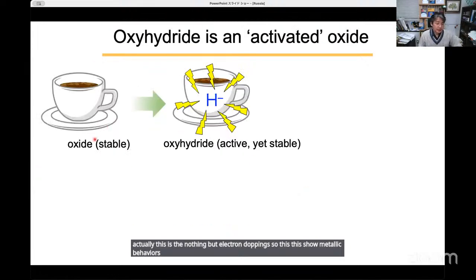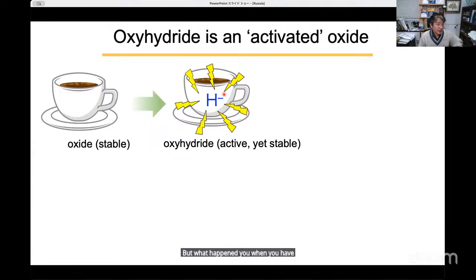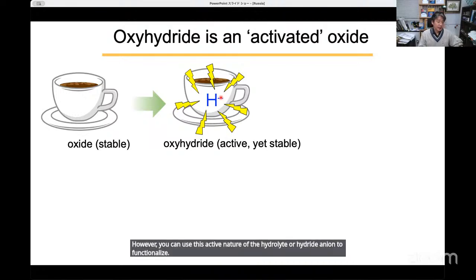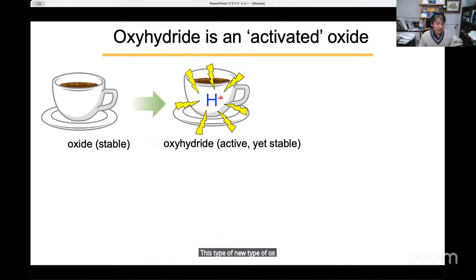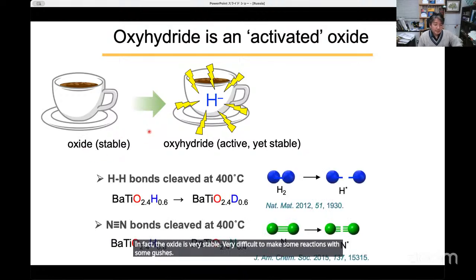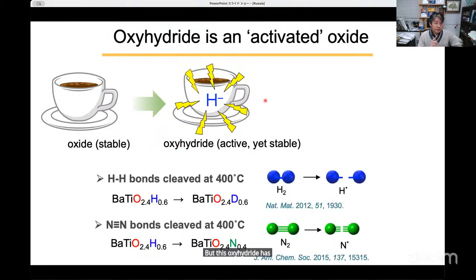Of course, oxide is very stable. You can use oxide as a coffee cup and so on. But what happens when you have a hydride inside a coffee cup? Then maybe you don't want to have coffee with this. However, you can use the active nature of the hydride anion to functionalize this new type of oxide, or oxyhydride, material. In fact, oxides are very stable and very difficult to make react with gases. But this oxyhydride has the ability to cleave small molecules.